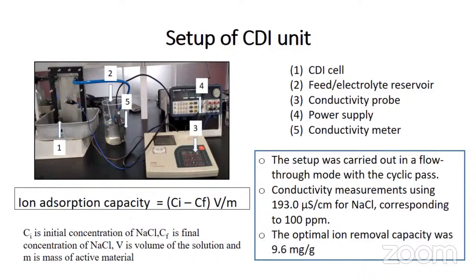This picture describes the CDI setup. The setup was carried out in a flow-through mode with the cycle pass. Conductivity measurements used 193 microsiemens per centimeter for sodium chloride, corresponding to 100 ppm. The optimal ion removal capacity was 9.6 milligram per gram. Here we measured that value from the ion adsorption capacity equation.